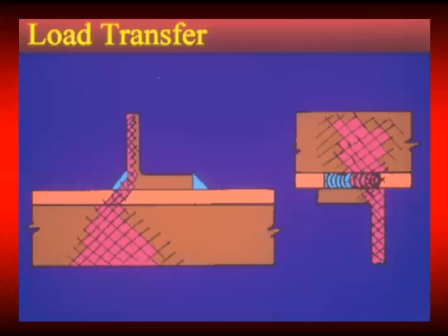Let's go one step further. By definition, that's either going to be the start of the weld or the crater, right? The welder might not carry the weld all the way out to the end. Or when the weld was struck, maybe the arc didn't strike and we didn't get good fusion at the beginning. If it's the crater, maybe the crater didn't get filled, or maybe there's a little undercut. The point is there's likely to be a workmanship defect there.